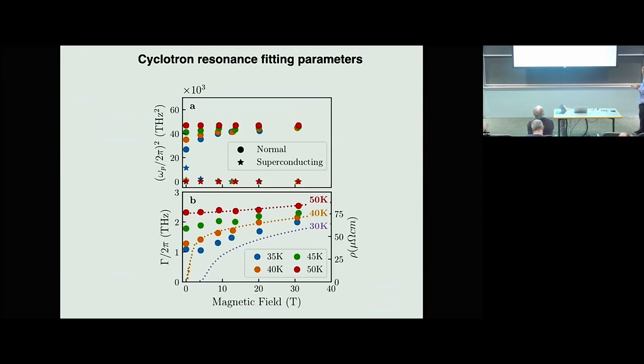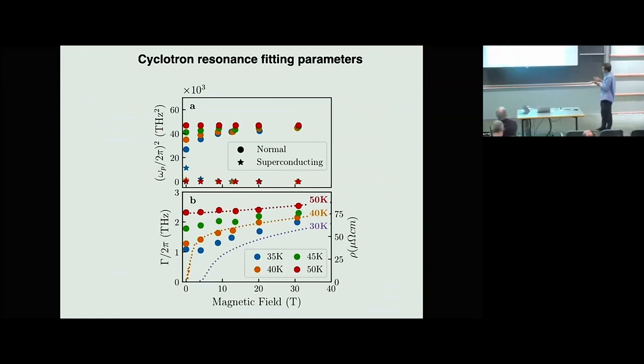This is scattering rate as a function of magnetic field. And you can see that there's a field dependence. I think the way I understand this heuristically is that there's a frequency dependence to the scattering rate, and as I push spectral weight to high frequencies, it becomes a high energy phenomenon and the scattering rate gets bigger. The question is, what's that functional dependence, and can we say something interesting about that? And I don't have a comment on that now.